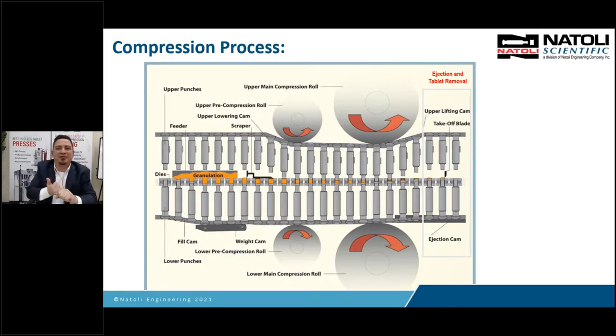One common problem I see, if you have a sticking issue, is people say let's add more magnesium stearate, that'll reduce my sticking. Well, a lot of times that causes even more sticking issues because the more lubricant you put on, the less bonding between particles will happen because you got a layer of lubricant there. So if the particles don't want to bond to each other, the particles are going to bond to the punch face. So adding more lubricant does not always fix sticking issues. I add lubricant to reduce the ejection force, and we use other techniques to reduce picking and sticking issues.